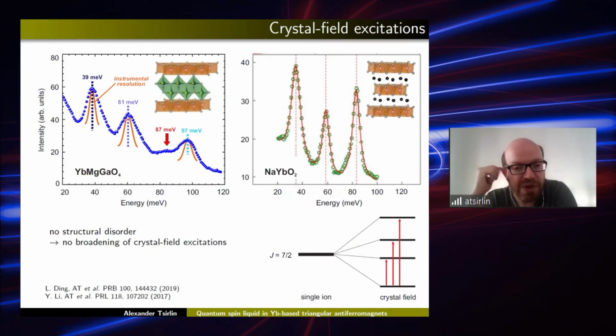So first of all, we wanted to make sure that the structural disorder has been eliminated, that the material is well structurally ordered. We already know that we should look at the crystal field excitations, right? So we expect 3 resolution limited peaks due to these excitations. That's what we tried to measure on the NaYbO2, and indeed we observed exactly what we expected. In the previous case, we had these very broad peaks, which were much broader than the instrumental resolution. Now we have 3 resolution limited peaks and no additional features like this one. So indeed, we have no structural disorder in the NaYbO2.